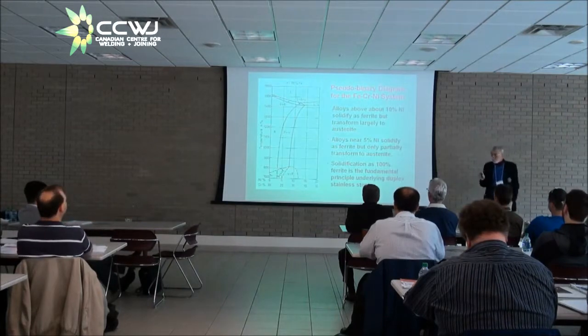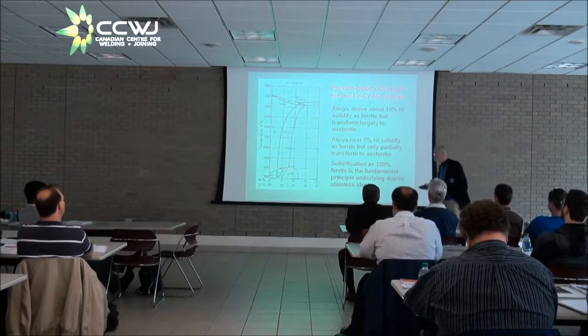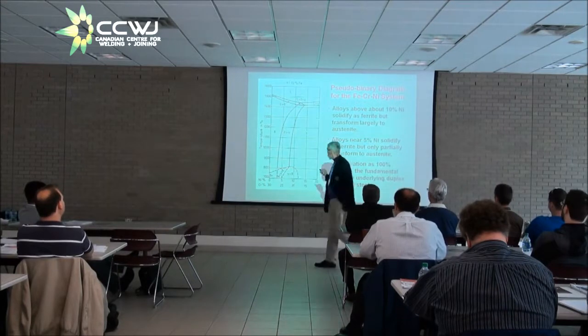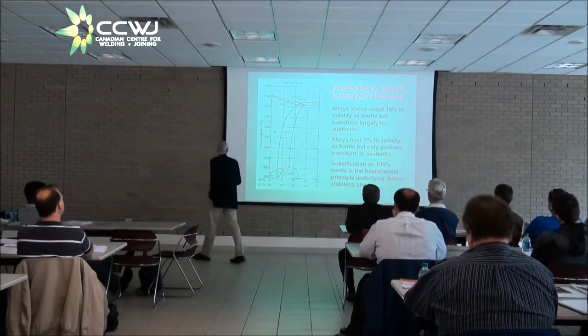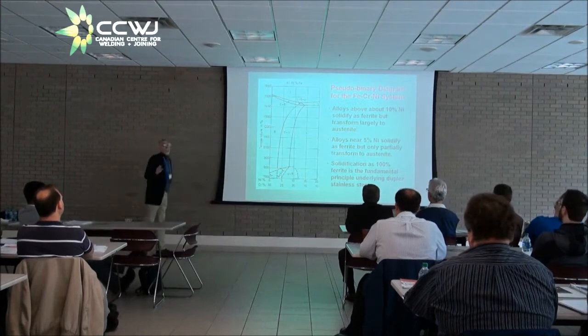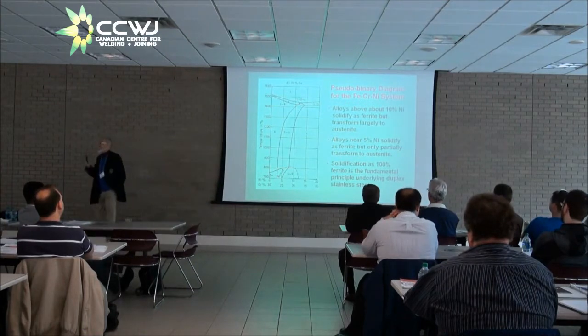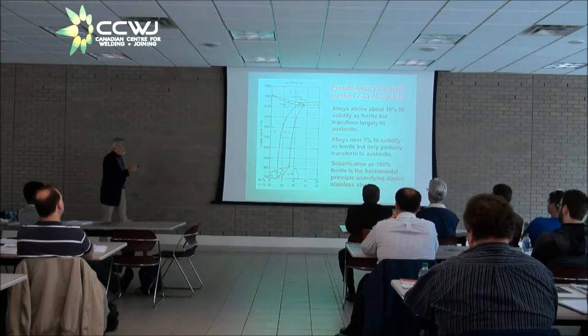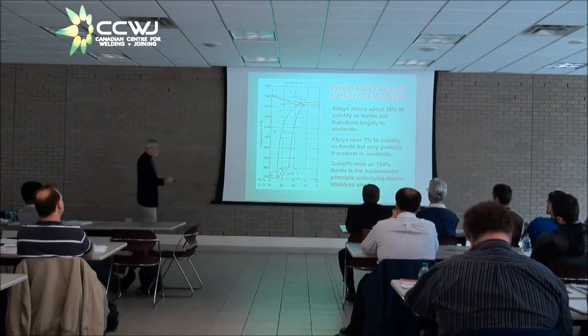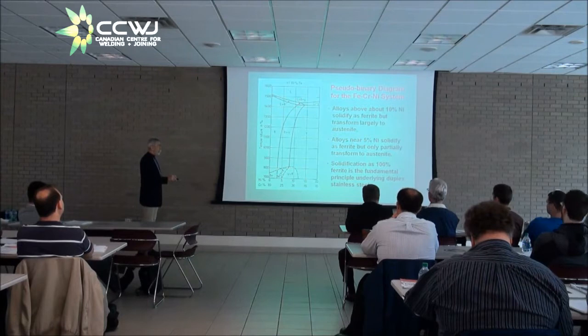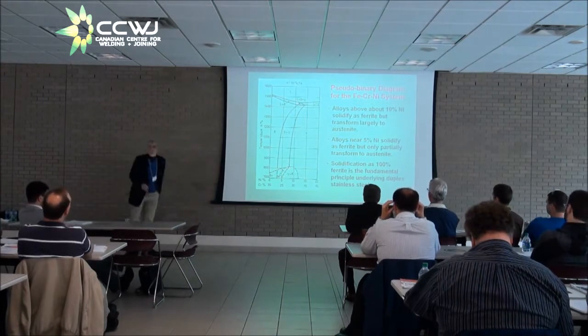Now, how do duplex stainless steels come about? What you see here is a section through a ternary iron-chromium-nickel diagram at a constant iron level. Okay, so it's 70% iron. And what you're doing as you go from left to right across this diagram is going from no nickel up to 20% nickel, and from 30% chrome down to 10% chrome.